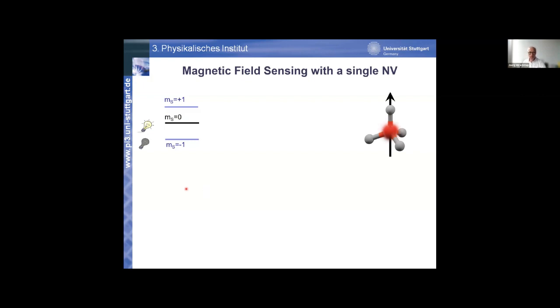Very simple. What I've shown here are the 3 spin sublevels of this NV center, which I use here as an example. This middle sublevel is the one where you can generate photons from, whereas the other ones are the ones where your system is rather dark. Now, we measure magnetic fields by driving the spin resonance. That is, we drive the spin transitions between these Zeeman levels here.